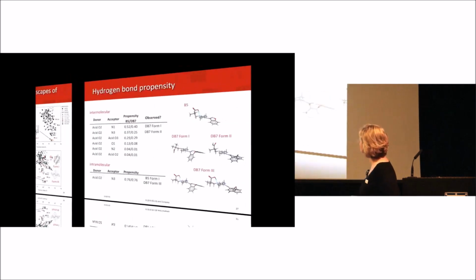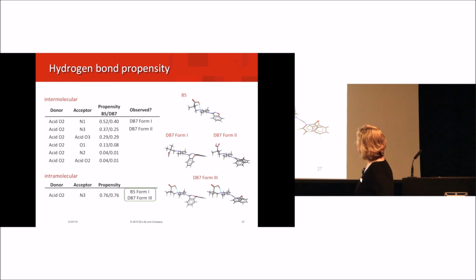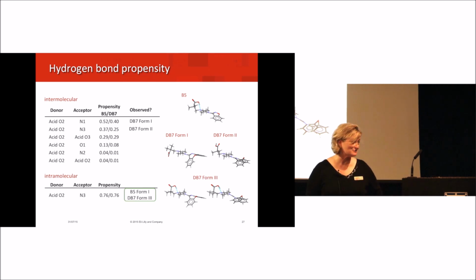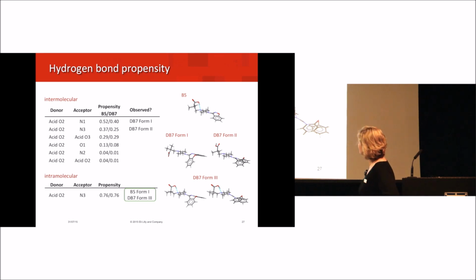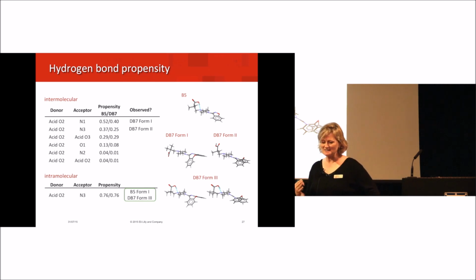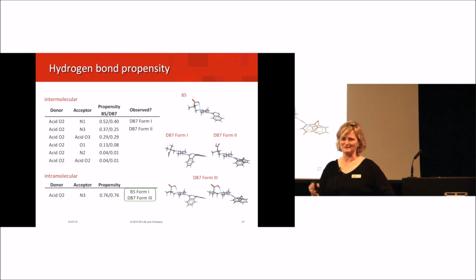Now, how did the informatics do? So in this particular instance, we have hydrogen bonds of the intramolecular variety being heavily favored. And in fact, in the only form of B5 and the least stable form of DB7, that's in fact what we see. But the most stable forms actually don't track with the highest propensity hydrogen bonds. And so this is exactly what we want to share, that I think hydrogen bonds are fantastic to look at and rationalize crystal form stability in terms of, but obviously there are a lot of interactions that make up our molecular crystals. And so in some respects, I'm kind of happy to have examples that show how well it works and where the areas of opportunity are.